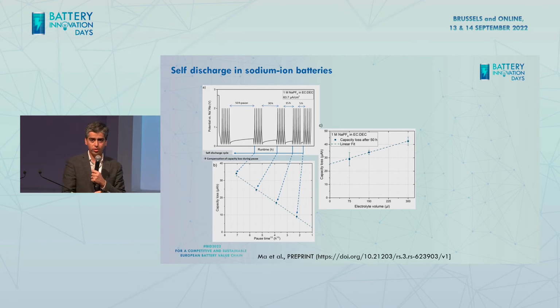And that's what we try to understand, to quantify such a small loss, because you may not see that actually in 50 cycles or 100 cycles. But when you go to commercial application, when your battery is supposed to work for 10 years, that's when such a small issue becomes big over 10 years. So that's what we try to understand.